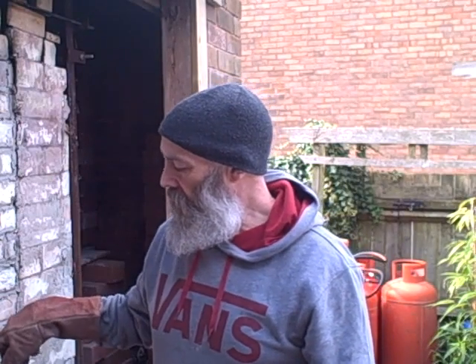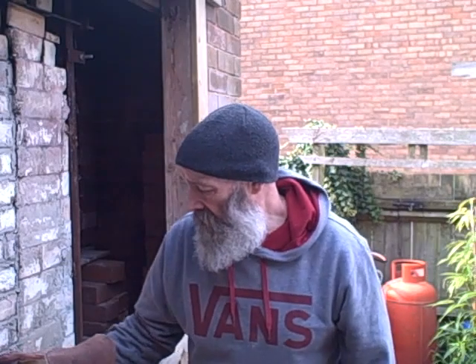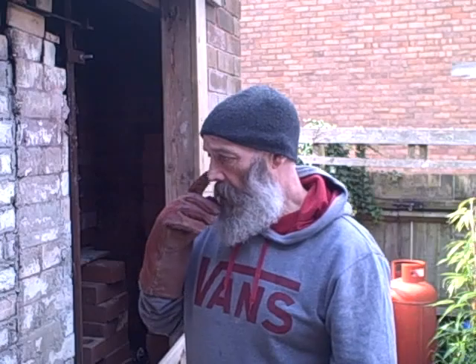Okay, right. Cone 10 is bending now, top and middle. It's right over. Bottom cone 9 is down and cone 10 is bending, so I'm not going to overfire it like I did the last one. I'm going to shut it all off now, so I'm going to show you how we shut it off.